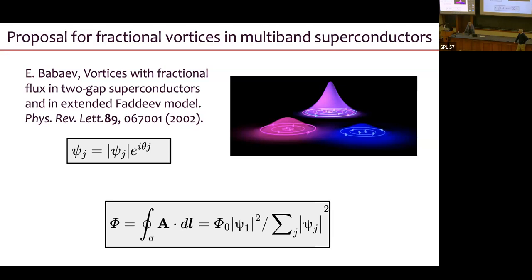We measured the penetration depth. And so my belief is that the penetration depth is larger than the coherence length because we are seeing vortices. We couldn't measure the coherence length, but we could measure the penetration depth. We can measure the penetration depth in two ways. One is by seeing what the spatial extent of the vortex is. And the other is by measuring how much the sample shields the flux from the field coil, a field coil pickup loop mutual inductance style measurement. And the penetration depth from those two methods was consistent with each other.